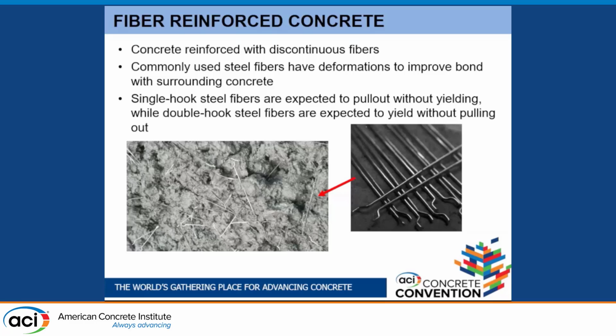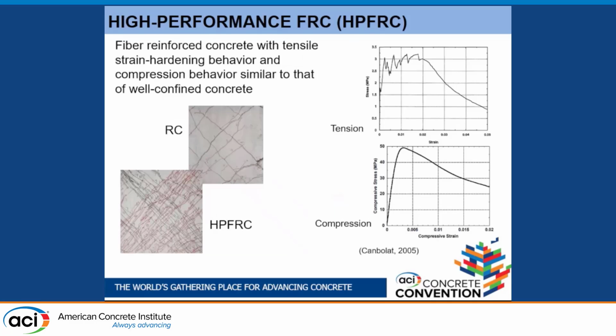And on the left, we see a photo of fibers being mixed with concrete. We can actually basically mix these fibers in a ready-mixed concrete plant for large-scale operations, and up to 150 to 200 pounds per cubic yard, which are very large dosages of fibers. We have managed to do that in large-scale operations with a good fiber distribution.